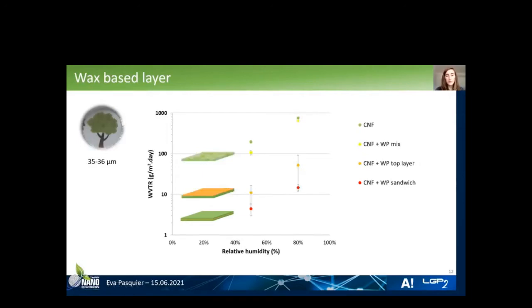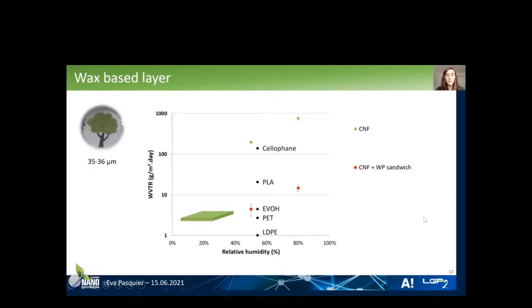Then we compared to other films that we processed in a different way. We mixed just the wax and the CNF together, but this didn't lead to any continuous layer, as the wax amount was too low. And then we also did a top layer of wax, but this was less homogeneous than the sandwich layer, so you can see that the deviation was way higher. And if you compare to commercial plastics that are available right now, you can see that we are a bit above the petroleum-based plastic, but still compared, for example, to PLA, we're really below.